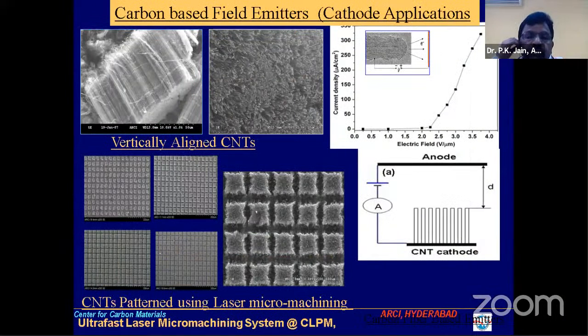Now we have also done some work on this. We have taken the aligned carbon nanotube and tried to measure the field emission properties. We have made the CNT cathode and then developed it. But we observed that the exposed surface is giving high emission as compared to the bulk. So we made a whole assembly and scraped it into columns, so that we get more surface carbon material rather than the bulk material. The side tip also emits electrons, and that's the reason this has given very, very high results, and this project was done for DRDO.